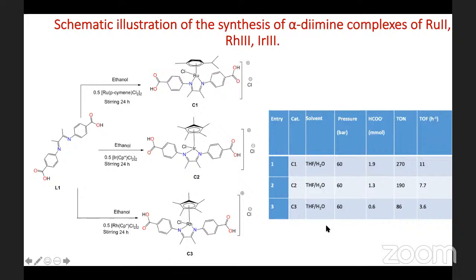So what we then rationalized was that because these are homogeneous systems, we can heterogenize them by making metal-organic frameworks. Already we have these carboxylic acid groups which are present. So it means we can take a metal salt or a metal cluster, and then under appropriate conditions, we can react that metal salt with the C1, we should be able to form a metal-organic framework with the ruthenium catalyst inside the pores. And of course, we should then apply it in the hydrogenation of carbon dioxide to form formate as a heterogeneous catalyst as opposed to being homogeneous.